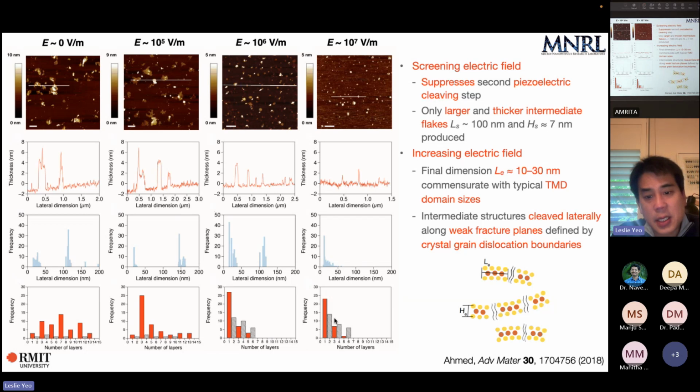But again, you see this asymmetry, even-odd asymmetry, and that's because when they have more odd layers, they become more piezoelectric, so they tend to get exfoliated more. So the 5 becomes 3, and so the 5 depletes, the 3 becomes less and becomes the monolayer, where the 2, 4, and 6 they stop there. Okay, so that's the mechanism we think is happening.